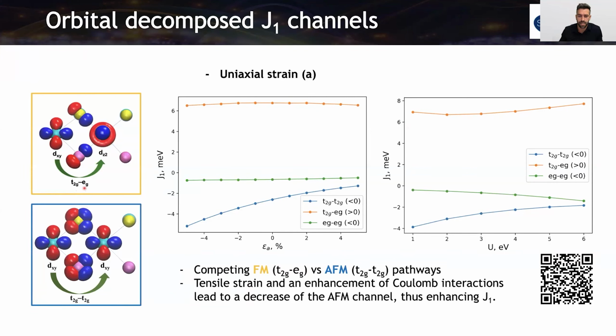This is a T2G to EG orbital interaction, a ferromagnetic pathway that is not being very affected by the strain. But we have here a T2G to T2G interaction, the DXY to DXY orbitals, that in this case is antiferromagnetic. And with this expansion, we are fighting against this mechanism. We are making it less antiferromagnetic, and then J1 is increasing in the material.